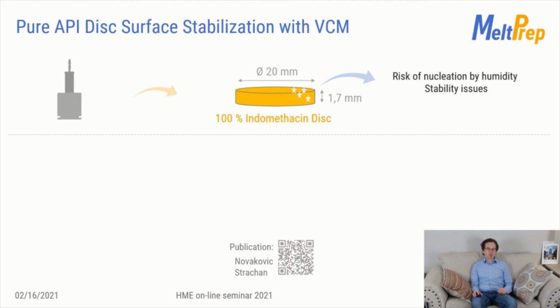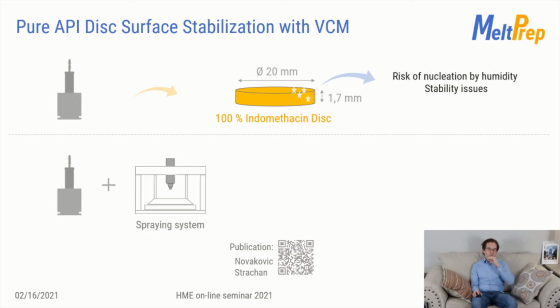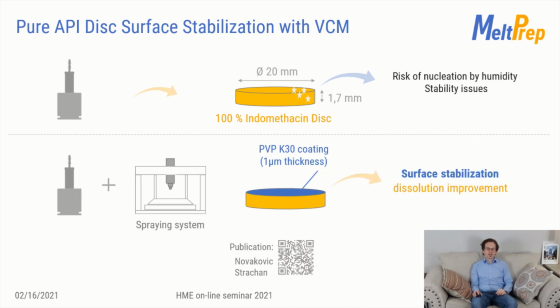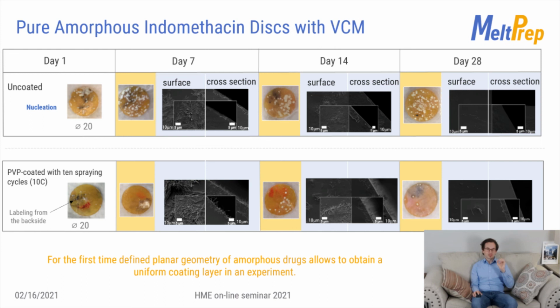But the smooth surface of the VCM samples allowed them to put a protective coating on top. It's just 1 micrometer thick. And you can see here a comparison on this slide. On top, you can see the uncoated samples, and on the bottom, the coated ones. What you can tell from the images, the surface of the uncoated starts to recrystallize on the very first day, while the coating increases the API stability significantly.